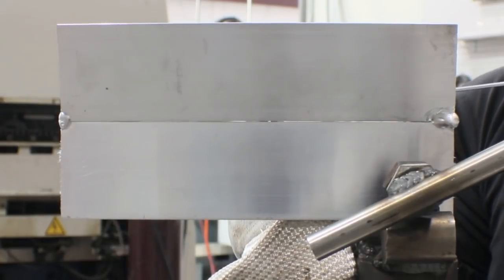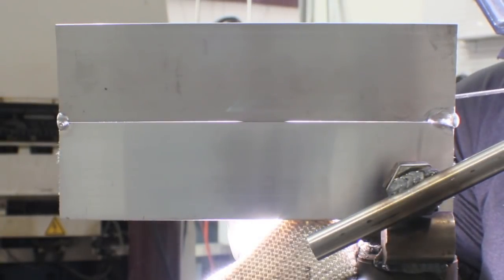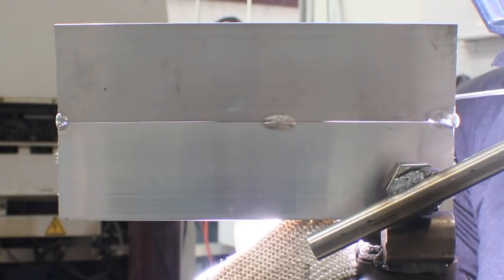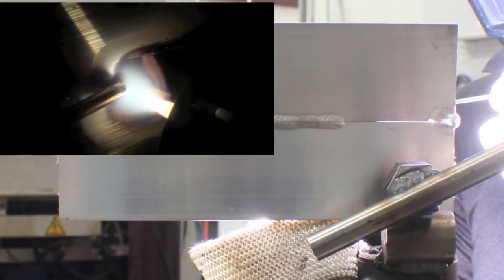I'm giving you lots of looks at this, as many as I can, because I figure I can't give you too many. Just see that cleaning action work. I'm just moving about anywhere from a sixteenth to an eighth of an inch in between dips. Here I'm going to show you something interesting. I'm going to show you the backside. You can watch that puddle kind of form and push through. There's oxide film on aluminum, so you watch it barely come through there, but it doesn't melt together yet. Now it finally joins together, but it's like there's a peel coat on there almost.